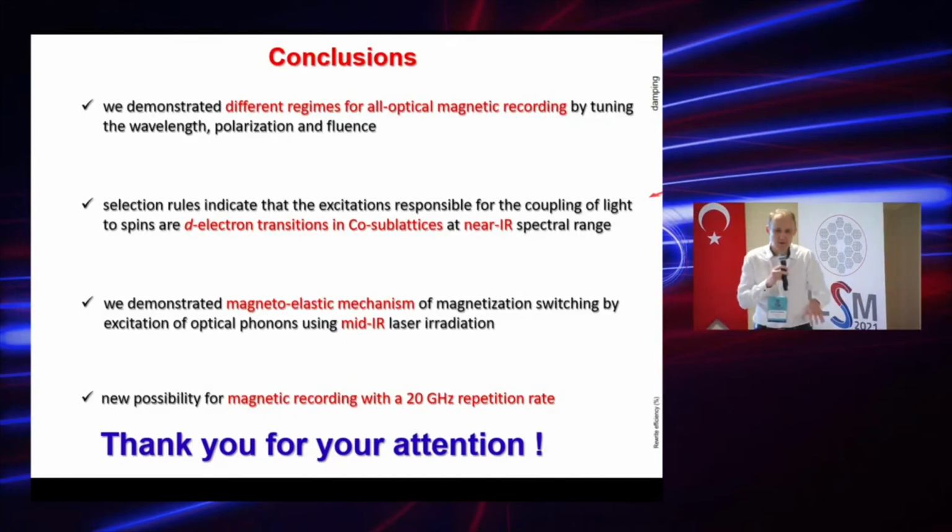So, after the microscopic redistribution of the ions, we expect excitation of different ions, for example in tetrahedral or octahedral symmetry, or 2+ or 3+. With different contributions to the magnetic anisotropy value, we expect an increase of additional magnetic anisotropy.